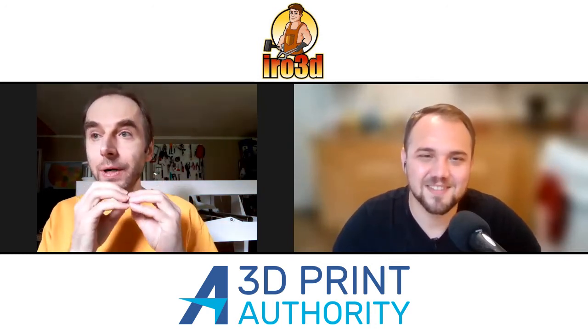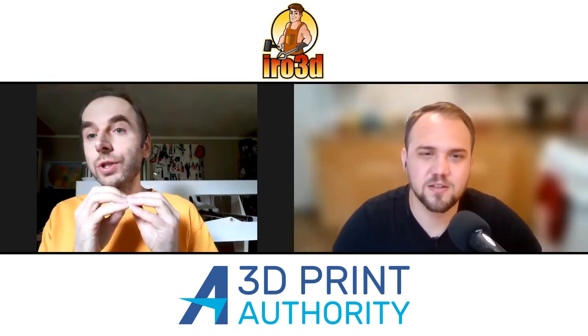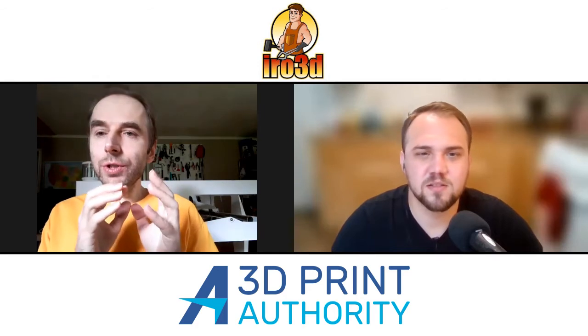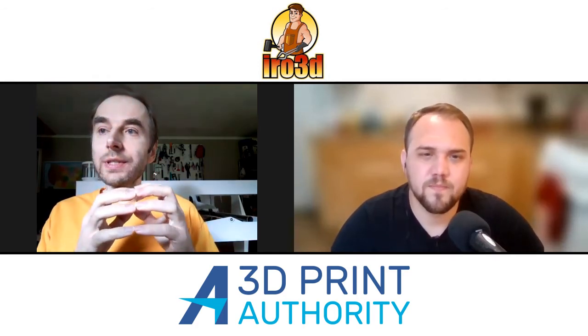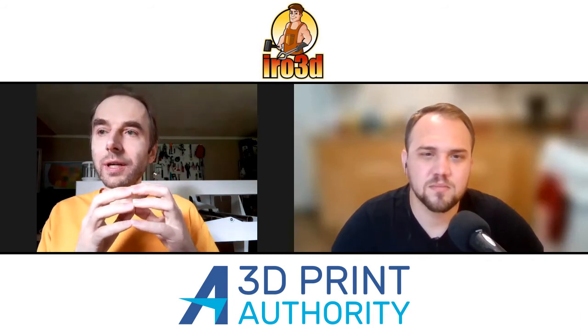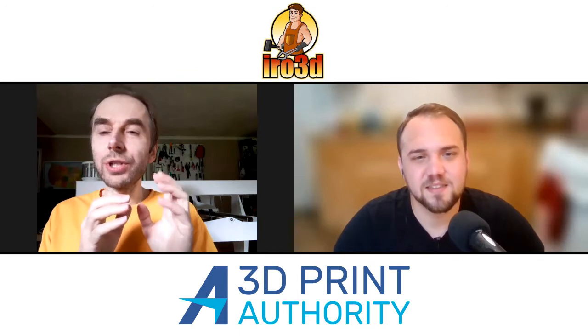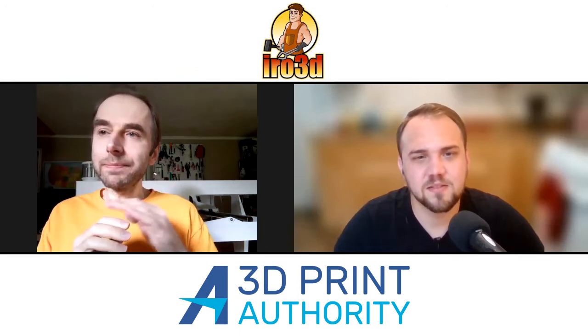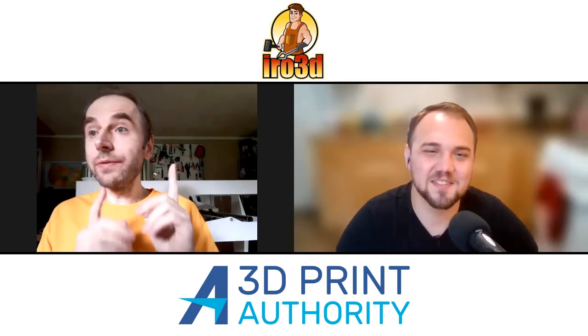Right. Because the metal powder doesn't melt. It always stays solid. So it holds the shape. There is some very small distortion due to the thermal expansion. When things expand, they expand unevenly, and so you have some small distortion, but generally it's very small. It's much smaller than what you have with sintering. So that's the advantage of this method.